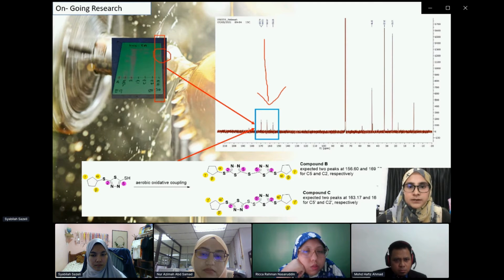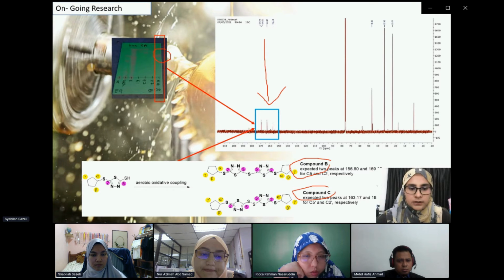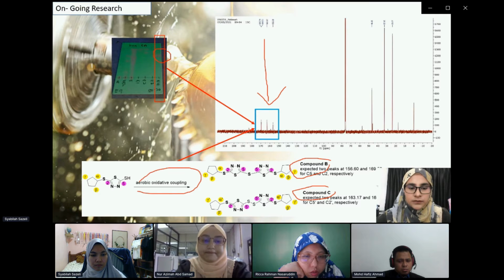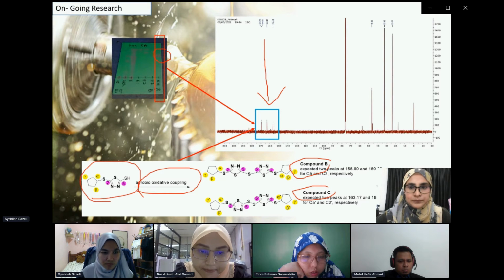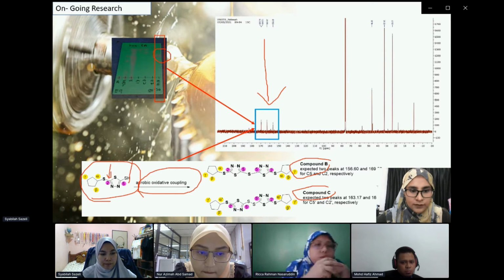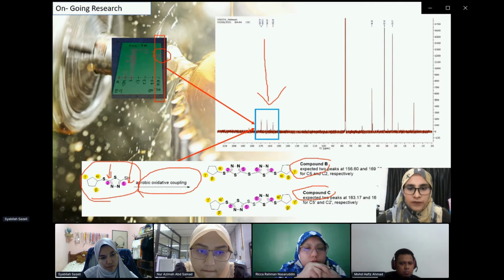So we expected that the peaks belong to a mixture of compound B and compound C, that both of the compounds are undergoing aerobic oxidative coupling of compound A at carbon number 2 and 5, thus producing a symmetrical disulfide. But then this probability needs to be double confirmed when we are able to resume the work.